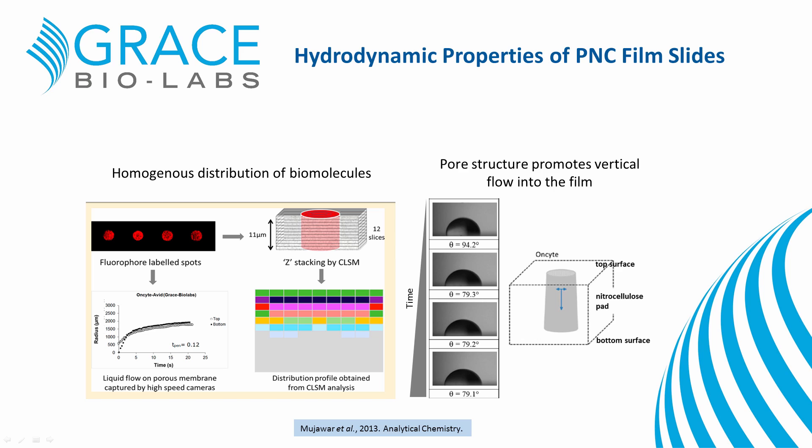The fluid dynamics of Oncyte PNC was recently modeled by a group in the Netherlands. The data demonstrate the desirable wetting and binding characteristics created by this film's pore structure. The investigators found Oncyte PNC to distribute spotted protein evenly on the spotted surface and into the film, with excellent vertical flow while limiting horizontal flow — perfect for higher density microarrays.